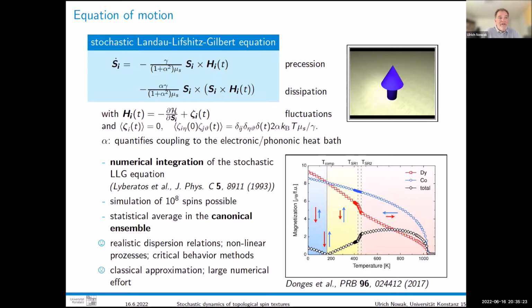There is an example here, a phase transition. That's the magnetization of some ferrimagnetic material, dysprosium cobalt, which has two sublattices, and you can, in a simulation, calculate the thermal properties. In that case, it is a reorientation transition from out of plane to in plane, then a phase transition to paramagnetic. All that can be calculated in principle. You need a lot of computer power for that. We simulate sometimes up to 10^8 spins. That is doable with certain methods on graphic cards and highly optimized.